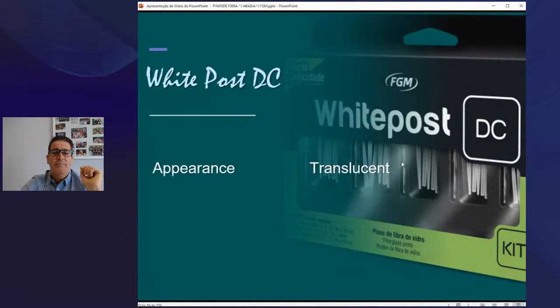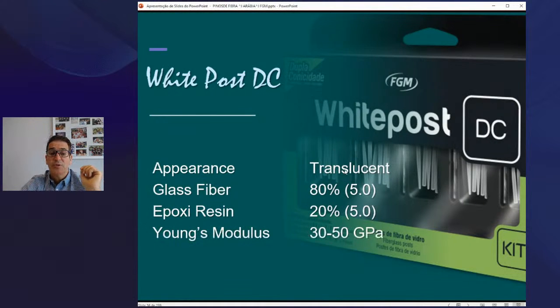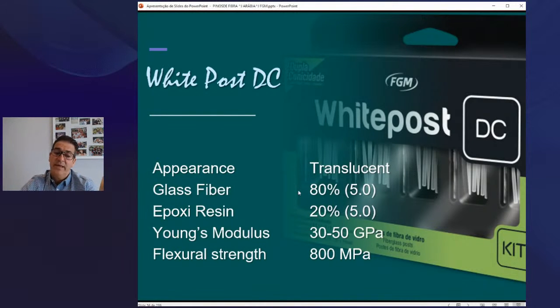The post, the DC, which is the one available in Brazil, is translucent because it transmits light. They have 80% glass fiber, a lot, 80 plus or minus 5, and epoxy resin, 20%. The Young's modulus varies between 30 and 50 gigapascals, depending on the thickness. And the flexural strength is 800 megapascals. It is extremely strong, 800 megapascals, has a nice flexural strength, and works very well.